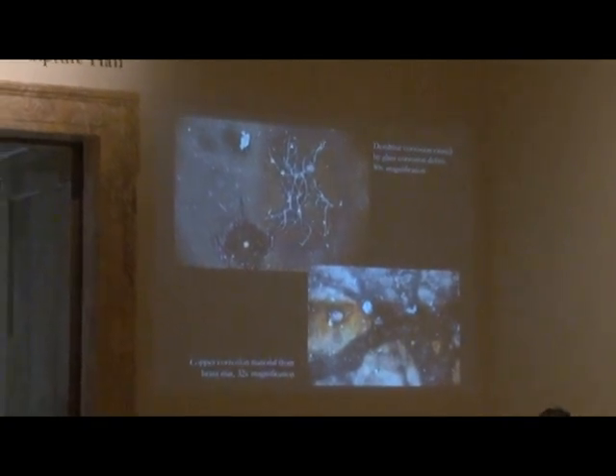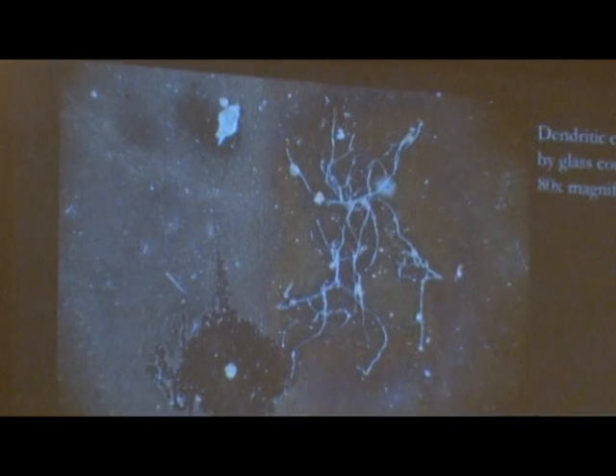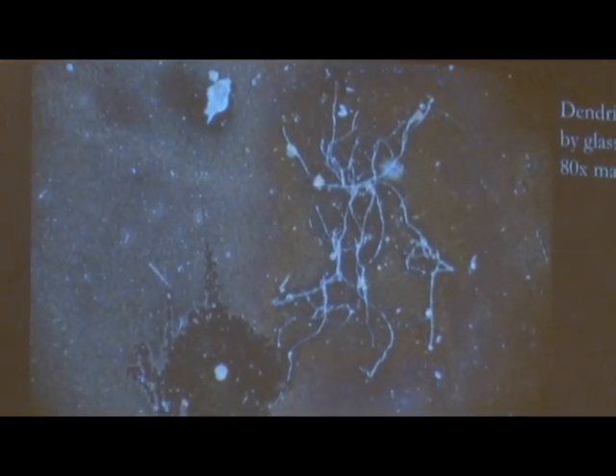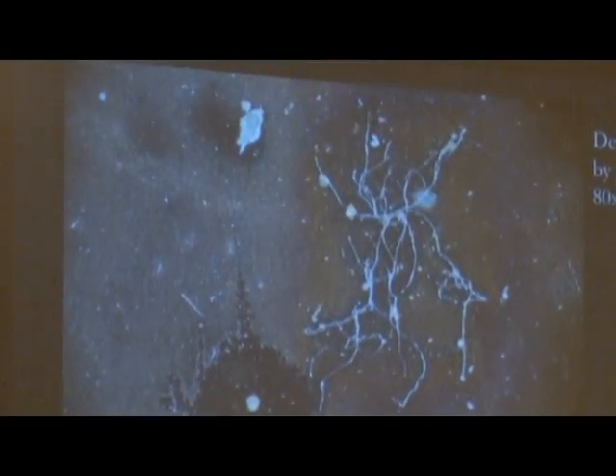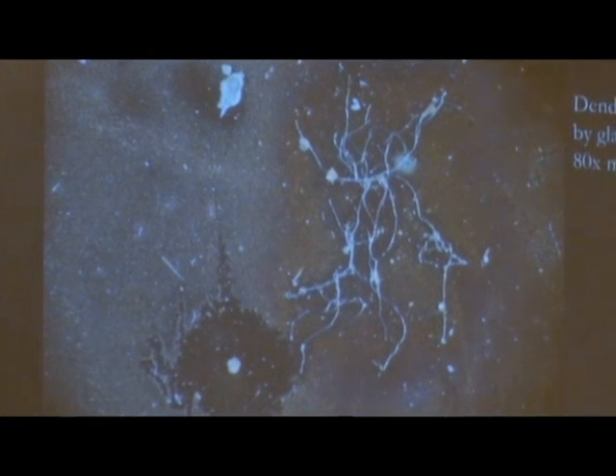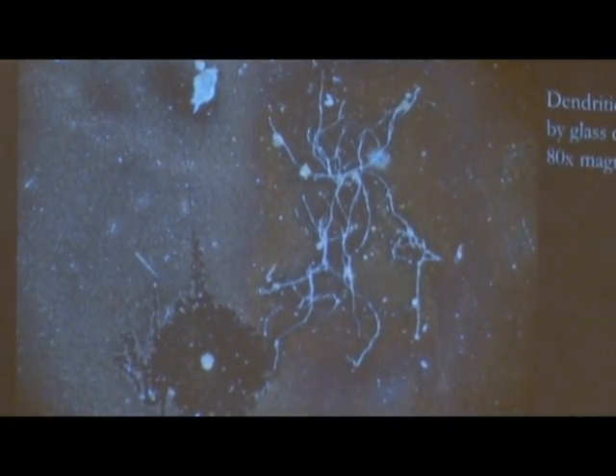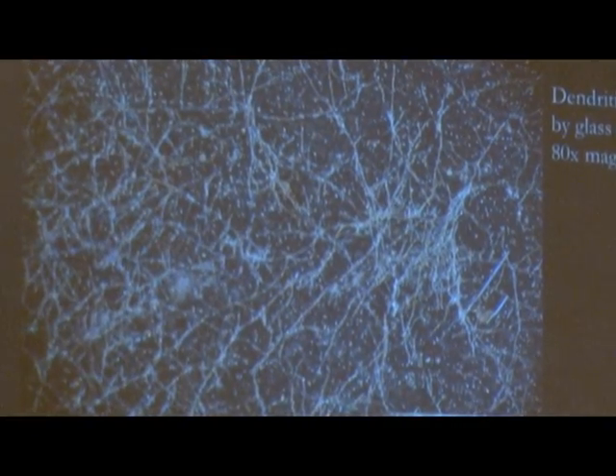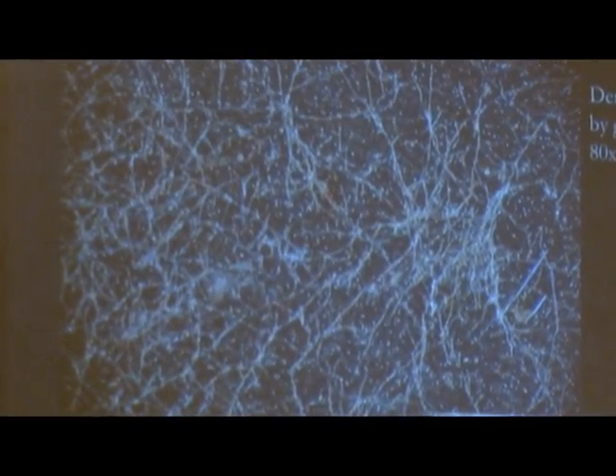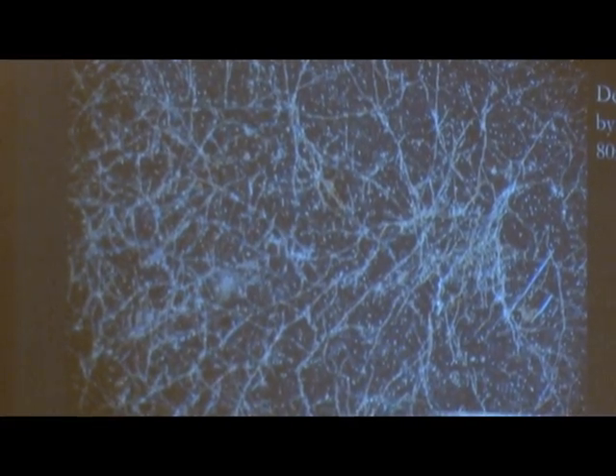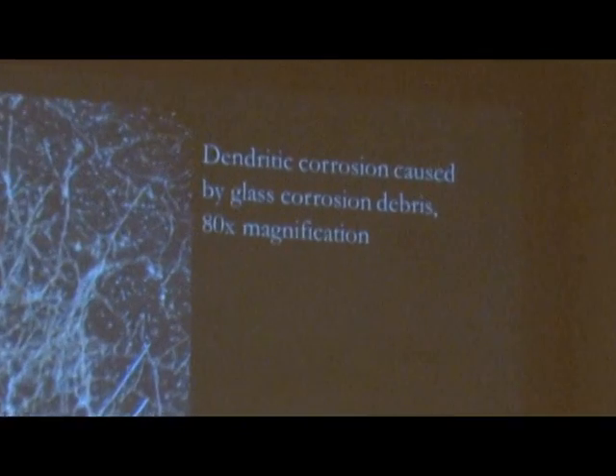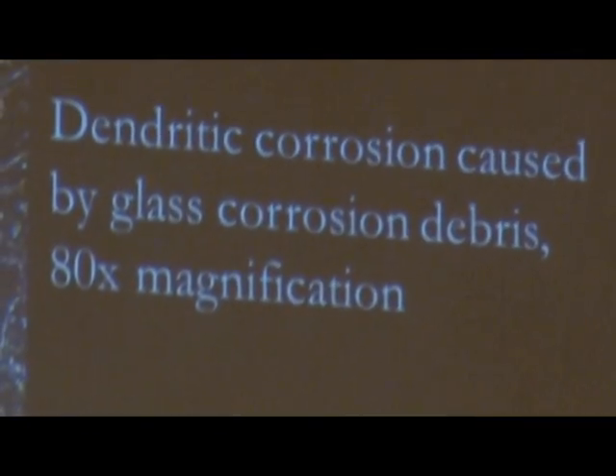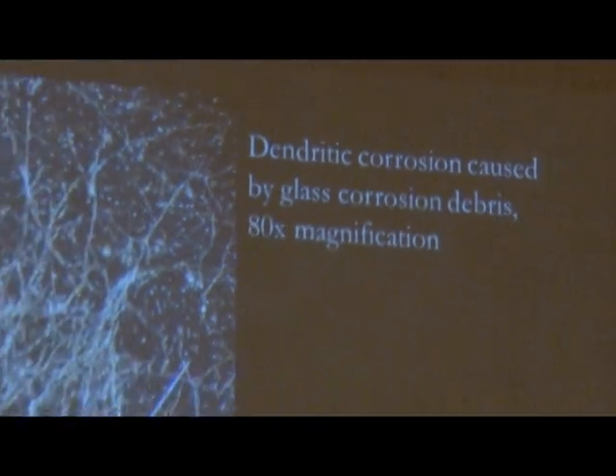And this is what happens to the plate when glass corrosion debris stays in contact with the surface. These are images of the surface of the daguerreotype at magnification. In the top image, you see dendritic corrosion material that was induced by glass debris. And when this condition advances even more, it looks like this. And this material formed really close to the plate, and it's really difficult to remove once it gets to this point. Glass corrosion only goes in one direction. Once it starts, it's going to continue to corrode, and there's nothing I can do to reverse this deterioration process.